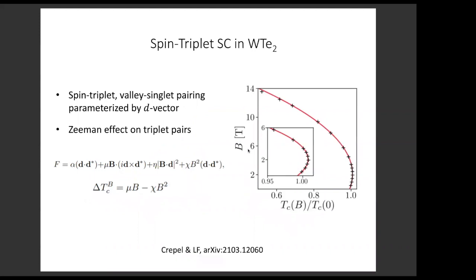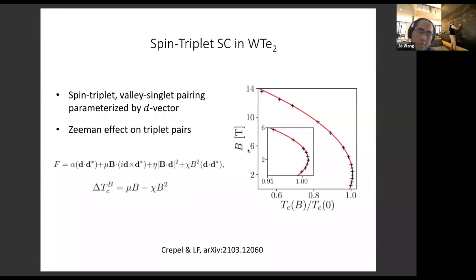So we then thought about how this can be understood within the framework of triplet pairing. In our picture of the triplet pairing, it has a D vector, because the triplet pairing has a spin quantization axis, and the spin quantization axis is free to rotate if you don't have spin-orbit coupling. And when you apply an in-plane magnetic field, the Zeeman energy of the triplet pairs would actually enter. So in the free energy, there's a term which is B dot D cross conjugate of D. This term essentially describes the effect of Zeeman energy of the triplet pair.